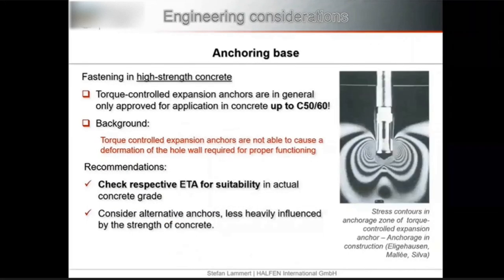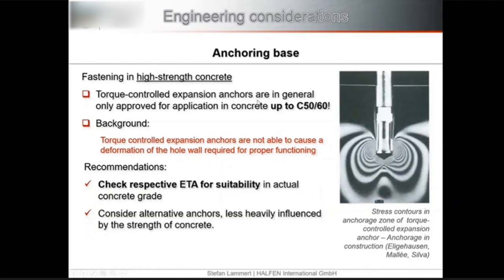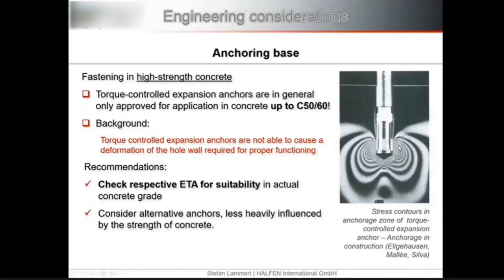Another important subject regarding the anchoring base is the suitability of expansion anchors in high-strength concrete. Torque-controlled expansion anchors are generally only approved for concrete up to 60 MPa, as they cannot deform the borehole around the expansion sleeve in concrete that is too hard. The recommendation is to check the European Technical Assessment for suitability in the actual concrete grade, and consider alternative anchors that are less influenced by concrete strength for high-strength concrete situations.